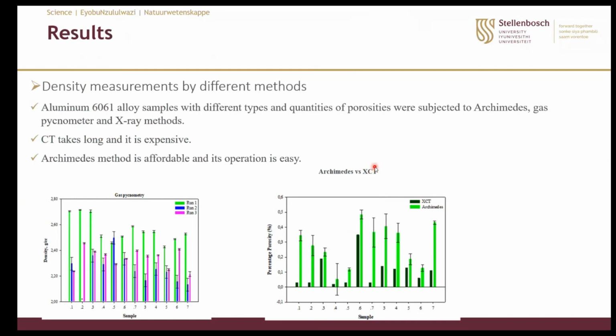We took measurements on 3 different days, and on those 3 different days we got different measurements. In both Archimedes and the gas pycnometer, we took precautions. Instead of handling the samples by hand, because some oil could be transferred from your hands to the samples, we used tweezers to handle the samples, and there were more precautions that we took. With Archimedes, we obtained that a number of samples had higher density values, with 42% of them having density values above the theoretical density from the literature. So as we went on, we still got different results.